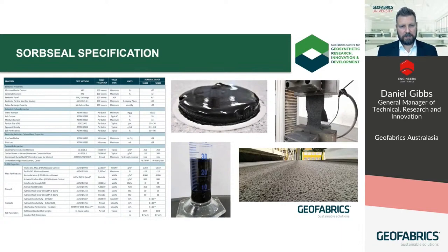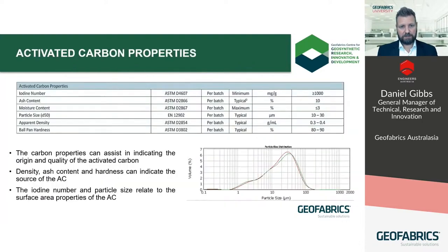We've also slightly lifted the hydraulic conductivity to a MARV of less than 5 by 10 to the negative 11 meters per second based on the data we've collected to date on these products. This could change, but that's where it's sitting at the moment. Remember, that's a deionized water hydraulic value, not a leachate value, which could change depending on the constituents and concentration of the leachate. So that really leaves the main additions to the specification being around the activated carbon itself.